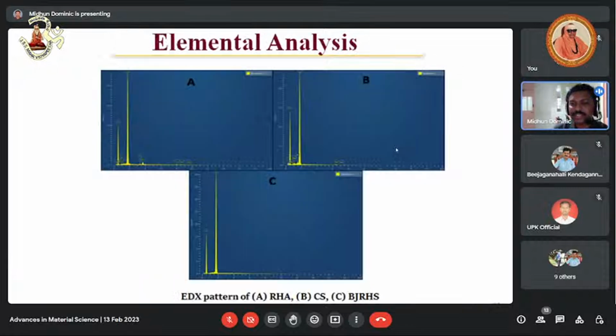And the elemental analysis was conducted by the EDAX technique, energy dispersive X-ray spectroscopy. I think the slide is somewhat blurred. Figure A is rice husk ash. Apart from silicon and oxygen, there are so many peaks: potassium, calcium, manganese, zinc, etc. Commercial silica also has silicon and oxygen, and apart from that it has aluminum and sodium, etc. But figure C, that is BJRHS, has only 2 peaks, one for silicon and the other for oxygen. So extremely pure nanosilica can be prepared by this treatment.